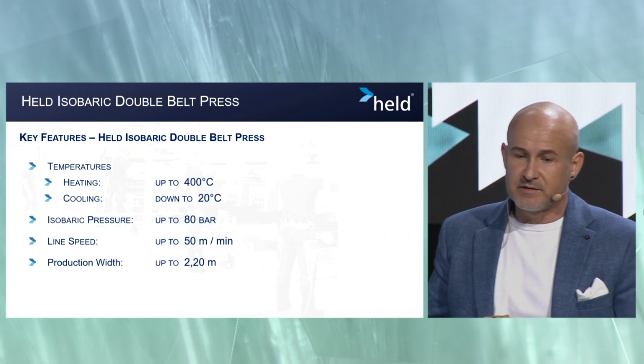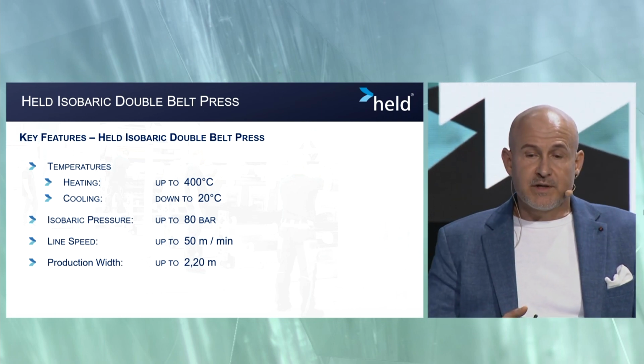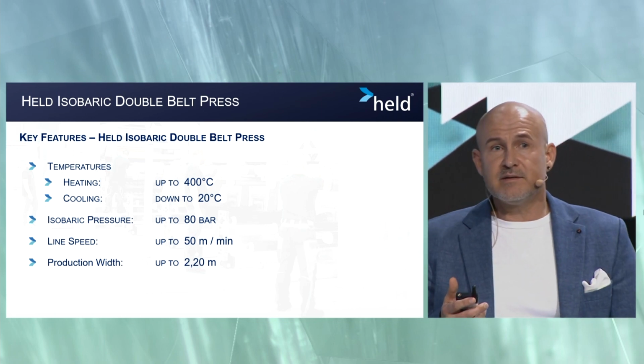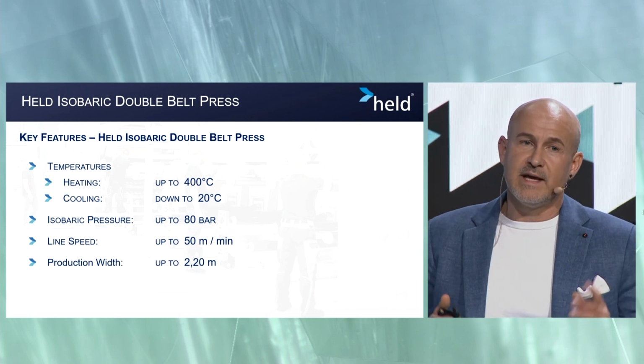Some key features of the Held double belt press. The machine can be heated up to 400 degrees C and cooled down to 20 degrees C. This enables the possibility to define very accurate temperature profiles for many different materials. So we have an isobaric pressure up to 80 bar. 80 bar is the same pressure you have around 800 meters below sea level, or the same